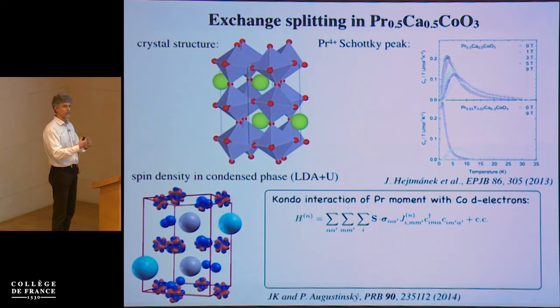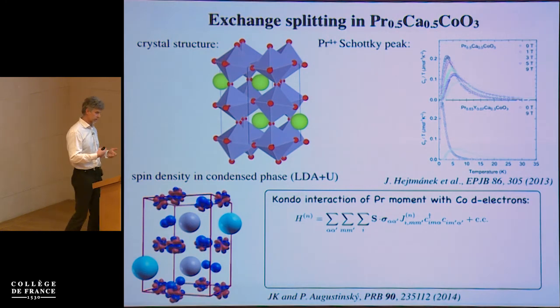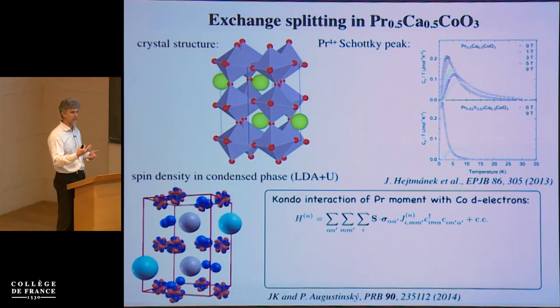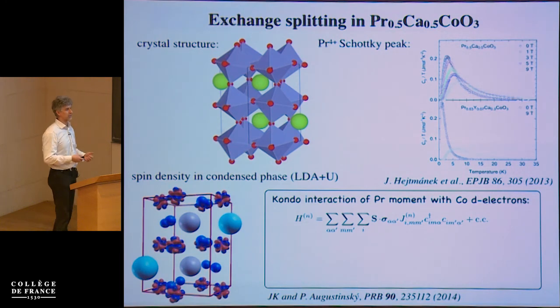The total spin moment per cobalt site is essentially zero, but there is a spin polarization which breaks the time reversal invariance, and there is an exchange field that acts locally inside the material, felt by the praseodymium moments.